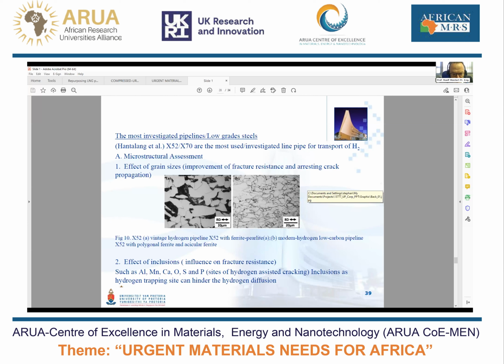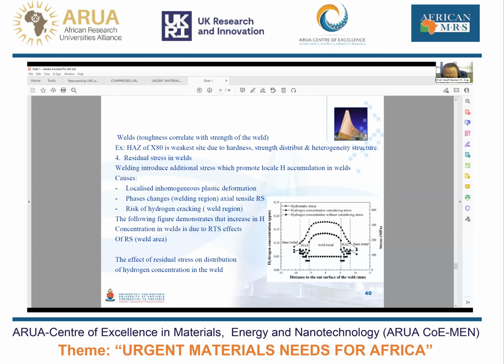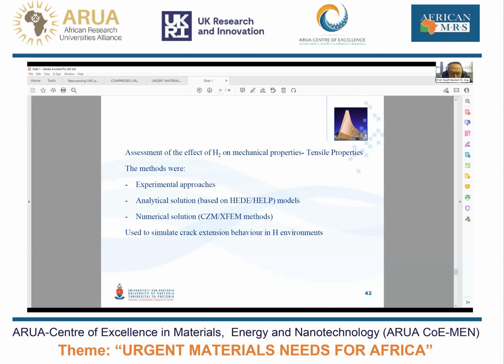Comparison of microstructures A and B there, A being a vintage X52 and B being a hydrogen resistant low carbon pipeline material, clearly shows the effect of the development in the latter number of years in terms of a better microstructure. So this particular schematic at the bottom of the page shows the preferential diffusion of hydrogen towards a weld metal. This is now in the case of weld metal with tensile residual stress, and it then just demonstrates that the welds are likely to be the areas that will accumulate hydrogen damage more rapidly than any other region.